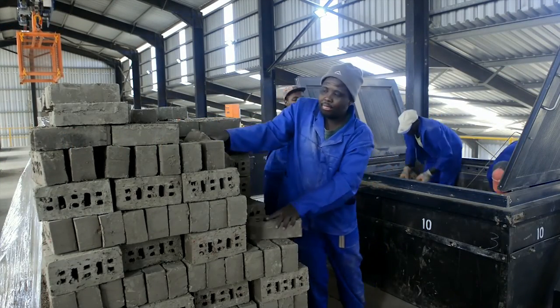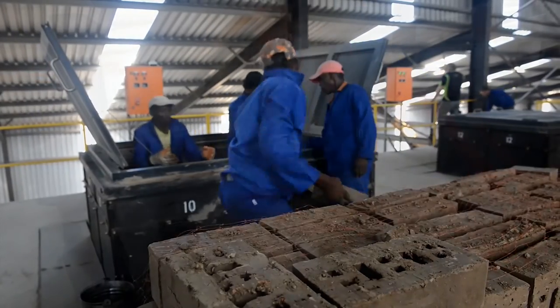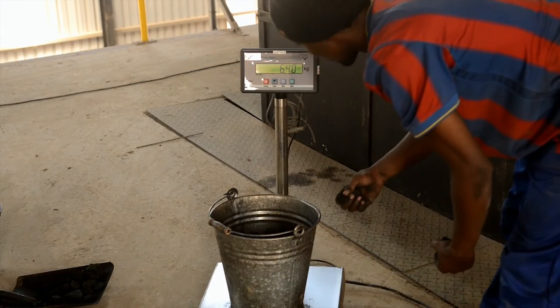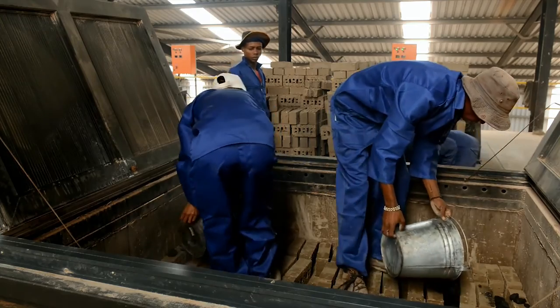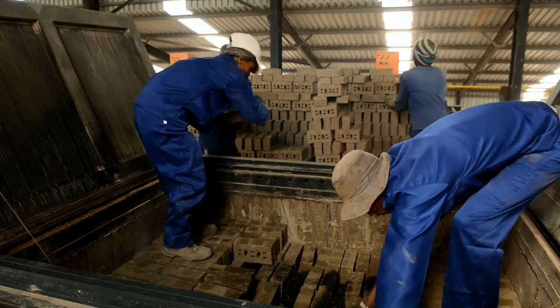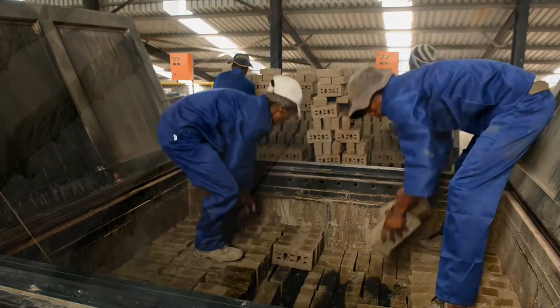Brick packing patterns are employed to allow the controlled flow of air within the kiln. External fuel in the form of small nuts is carefully measured into buckets and taken to the kiln being loaded. The coal is specifically placed within the batch to enable even firing and maintain heat within the kiln. A stock brick batch is made up of four equally spaced opposed layers, with each batch typically containing between 456 to 464 bricks. Fourteen of these batches are loaded into the kiln at any one time.